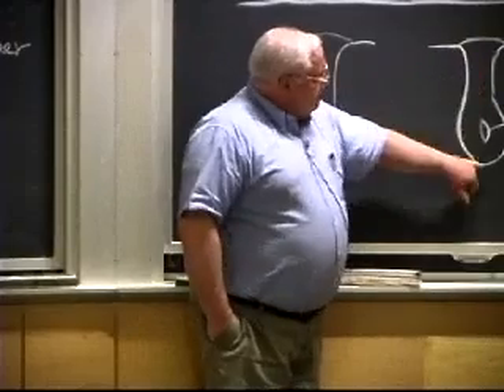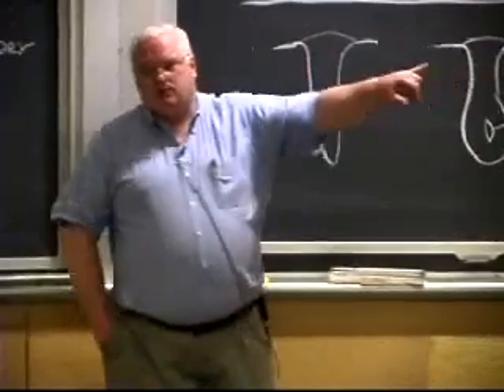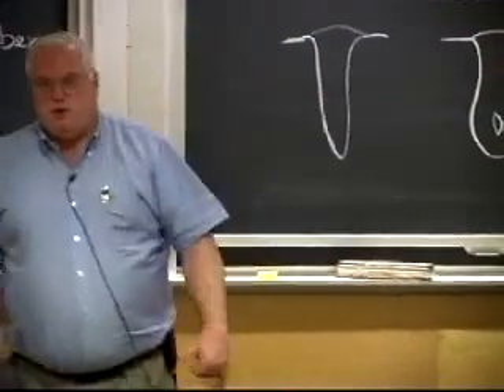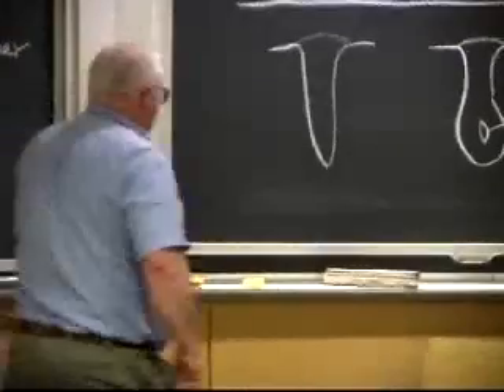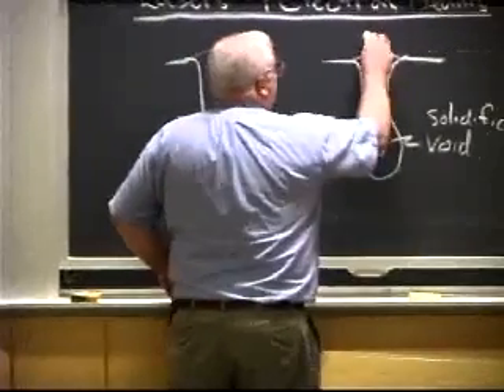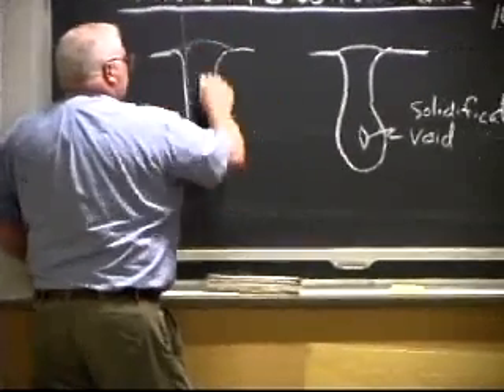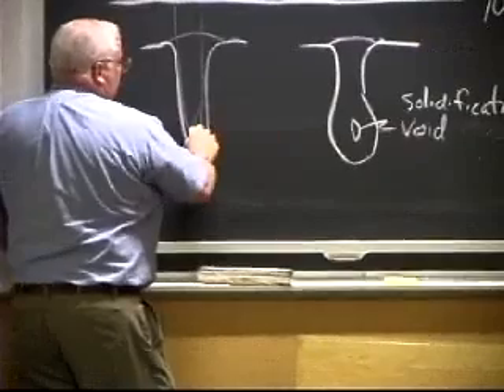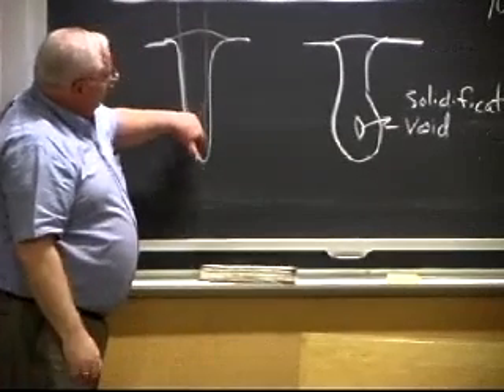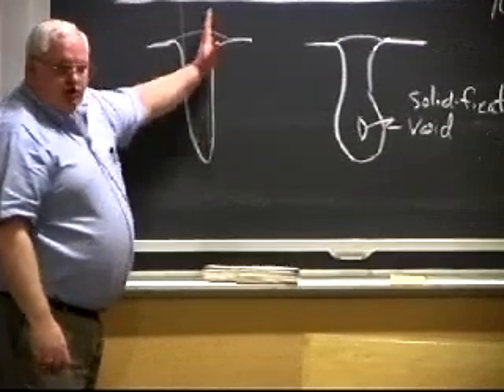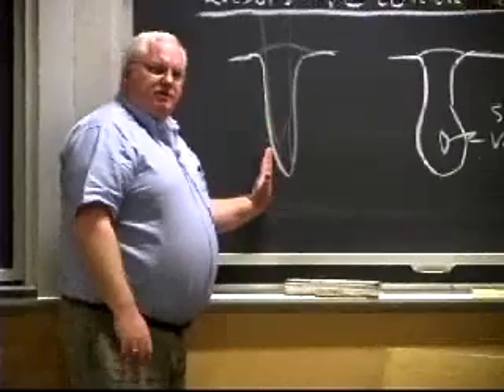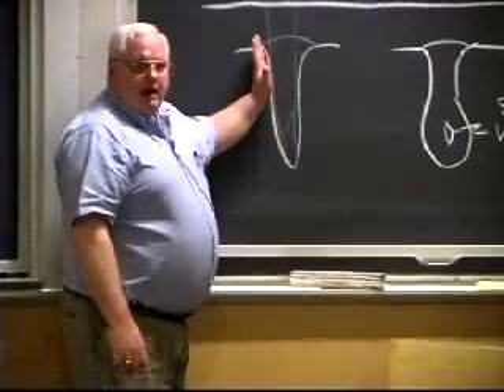Another concern is that you have to have the proper focus with your optics, whether it's electron beam or laser optics. You want to have a long focal length such that the beam comes in and can be focused somewhere down towards the bottom of the hole, typically, so that you can get nice parallel sides, or maybe even very slightly angled sides.